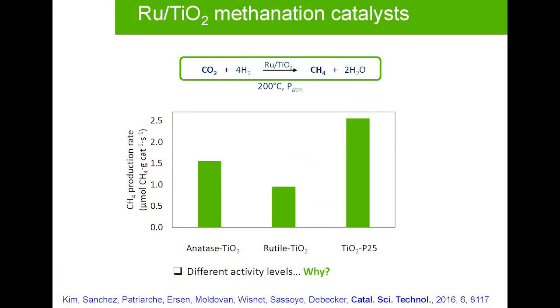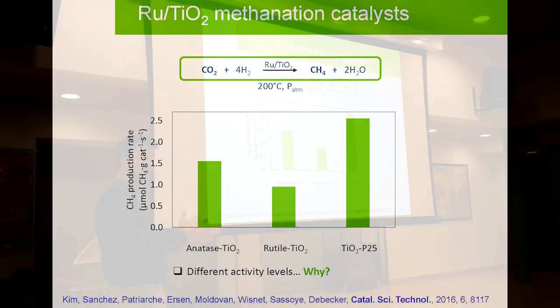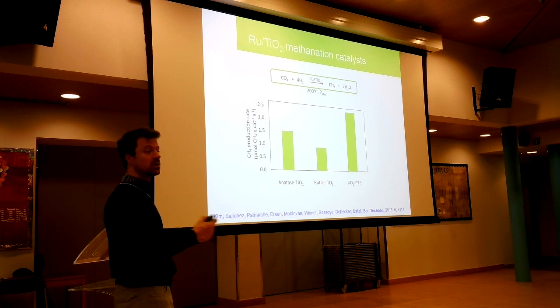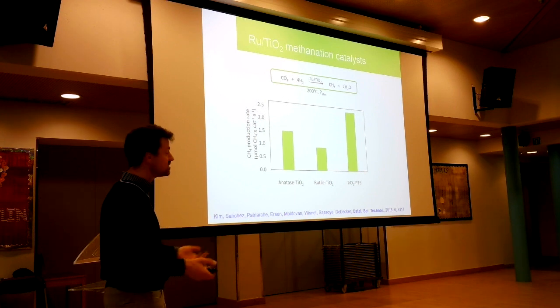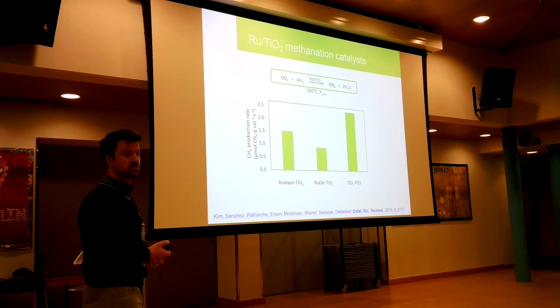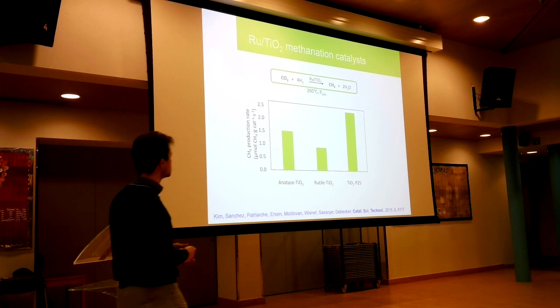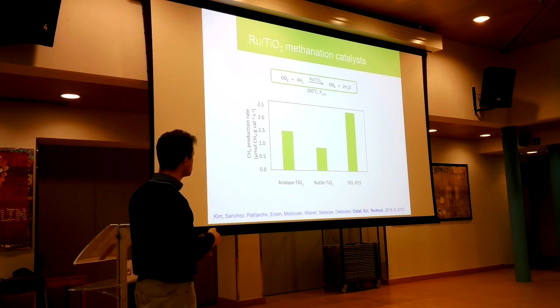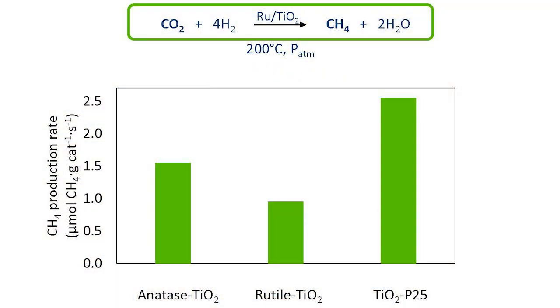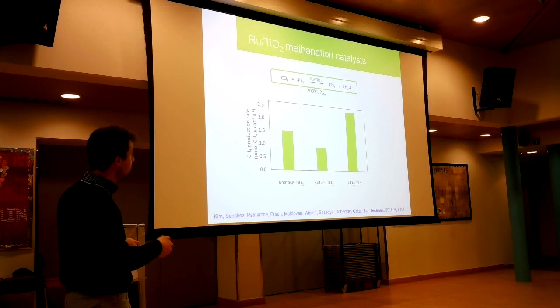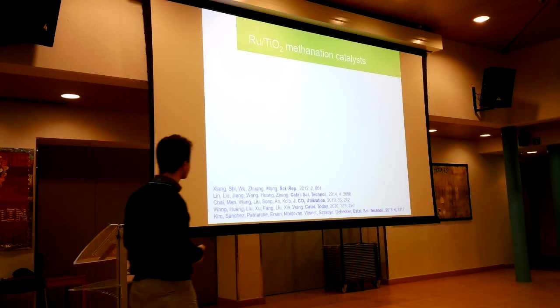As a reminder, what is active is the ruthenium, not the titanium, but yet when you deposit it on different phases, you get different catalytic results. So that was a bit intriguing, and we wanted to go further. This one is not so good on rutile, anatase is okay, and P25 is much better, while P25 is just a mixture of those two normally, so it's a bit surprising. Right? So the question was why?